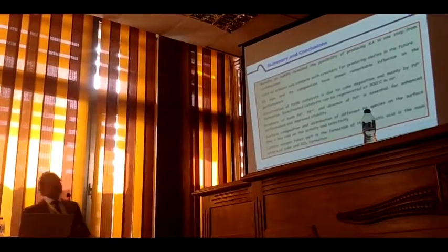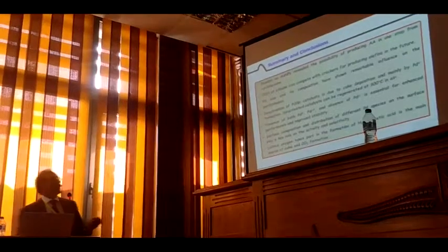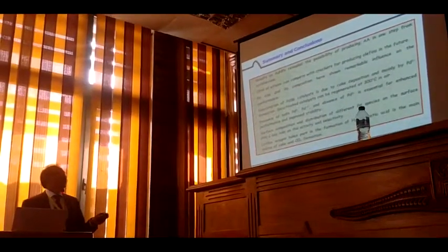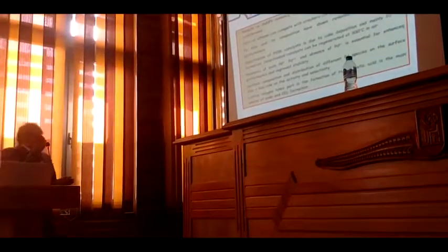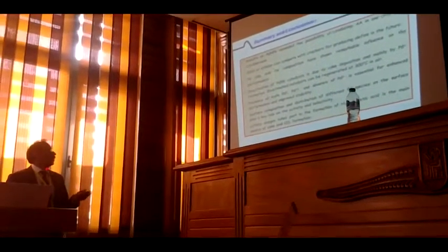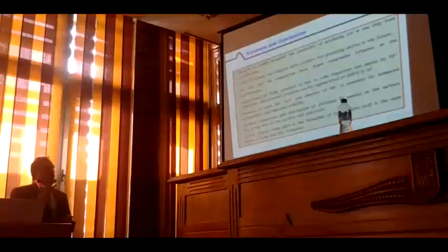So now I have shown the possibility of forming adipic acid in one step from cyclohexane using gold nanoparticles, and oxidative dehydrogenation of ethane may compete with steam crackers in the near future, and palladium size and its composition have shown remarkable influence on the activity and selectivity. Deactivation of this catalyst is due to coke, and mainly due to, I skipped this, palladium delta minus formation species, and surface composition and distribution of different palladium species on the surface play a key role on the activity and selectivity. Lattice oxygen takes part in the formation of water, and acetic acid is the main source of coke and carbon dioxide formation.